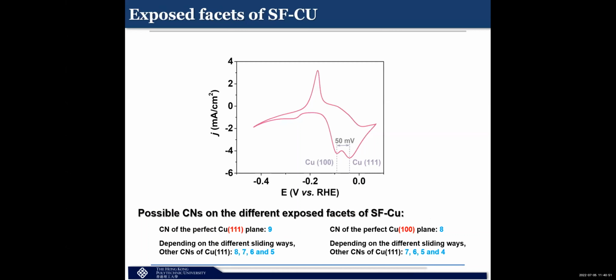Okay, so then we also tried to find out the exposed facets from this measurement. We found basically it is copper 111. The exposed plane is copper 111 and 100. Okay, so they have different planes. Then we have some simulation telling us that there are other possibilities for the coordination number.